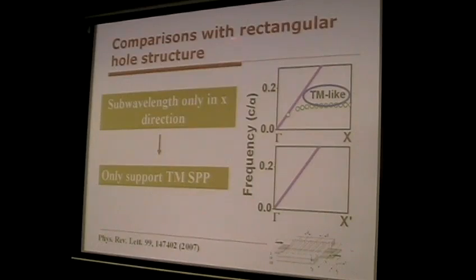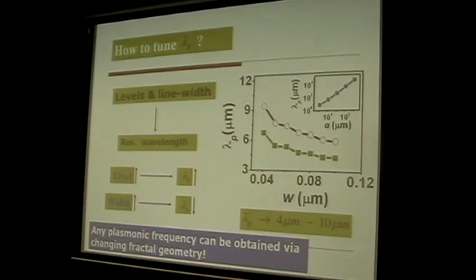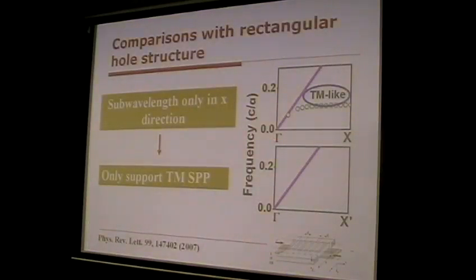Okay, if you compare our structure with this rectangular hole structure, we found that indeed this structure only supports TM polarized surface plasmon. So by comparing this one with this one, you can clearly see that the advantage of our structure is very clear.